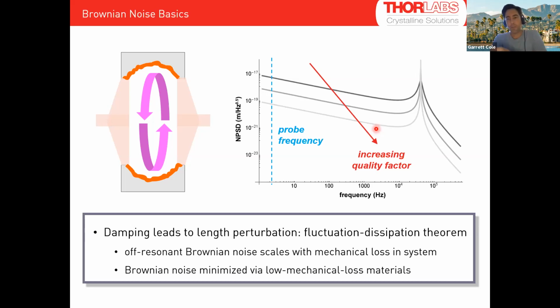As I increase the mechanical quality factor, I'm going to start packing the motion into the resonance, right? So I'm bringing down the tails, but I'm packing the motion into the resonance there. If I integrate over all frequencies, I'm going to get the same value because that's just proportional to temperature. So I'm going to pick up motion on resonance, but I'm going to drop motion off resonance here. And let's go to the most extreme case. Let's just make up a system that has 0 elastic loss. It would have a delta function at its resonant frequencies and then no motion anywhere else, right?